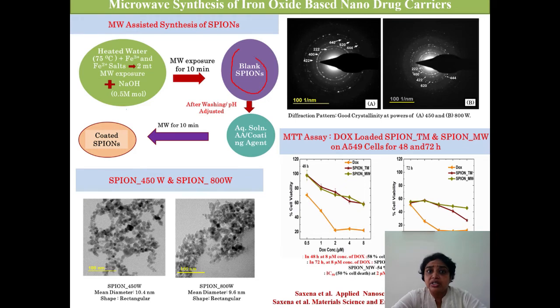Then we got iron oxide and, after washing it, we coated it with different kinds of amino acid, and then this coated material was loaded with drug and went for testing of the drug delivery and encapsulation efficiency. MTT assay was performed on this drug loaded iron oxide which was synthesized. We found it is superparamagnetic at room temperature, with very low coercive field. In addition, here we can see the crystallinity of the synthesized SPIONs was very good.